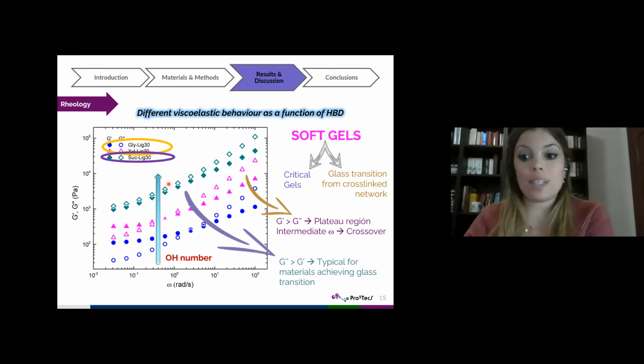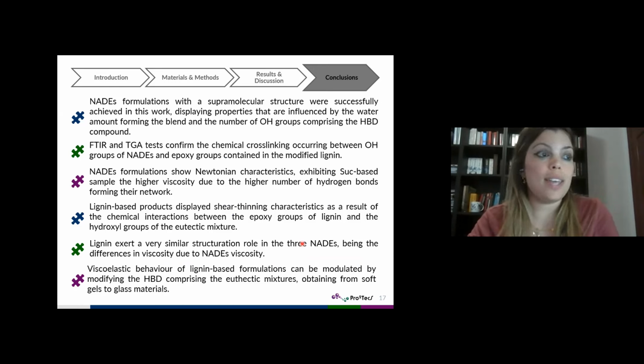Well, attending to the previous discussion, I can conclude that NADE formulations with a supramolecular structure were successfully achieved in this work, displaying properties that are influenced by the water amount forming the blend and the number of hydroxyl groups comprising the hydrogen bond donor components. Infrared spectroscopy and thermogravimetric analysis tests confirm the chemical cross-linking occurring between hydroxyl groups of NADEs and epoxy groups contained in the modified lignin. NADE formulations show a Newtonian characteristic, exhibiting the sucrose-based sample the higher viscosity due to the higher number of hydrogen bonds forming their network. Lignin-based products display shear thinning characteristics as a result of the chemical interaction between the epoxy groups of lignin and the hydroxyl groups of the eutectic mixtures.